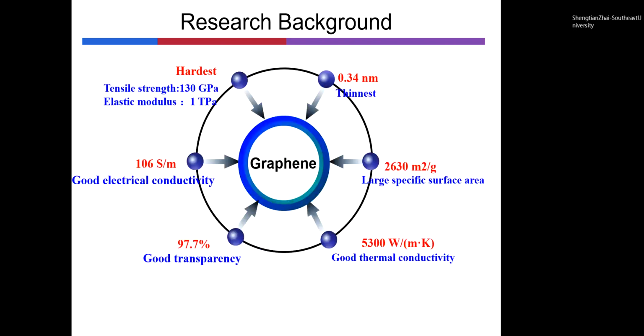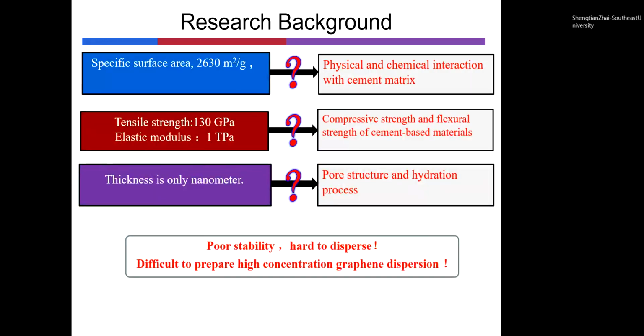Graphene, as a two-dimensional material with excellent comprehensive properties, has become a research hotspot. Tensile strength is 130 GPa. Elastic modulus is 1 TPa. Thickness is only 0.34 nanometer. As we can know, graphene has many advantages, and then how do these properties affect the cement-based materials, such as physical and chemical interaction with cement matrix, compressive strength and flexural properties, pore structure and hydration process.